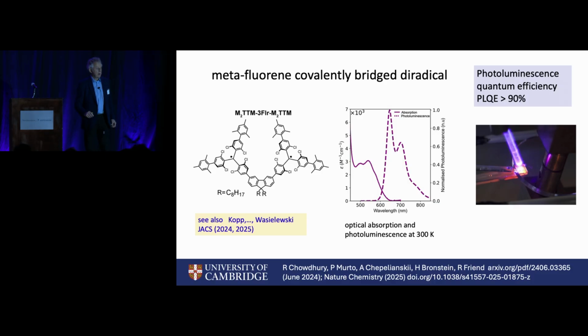These are very, very bright. They're close to unity luminescence yield. I mean, here is a sample excited down a light pipe with some blue light, glowing very, very efficiently in air. These are measurements that Alexei Cheplyansky in Paris was doing on these materials.